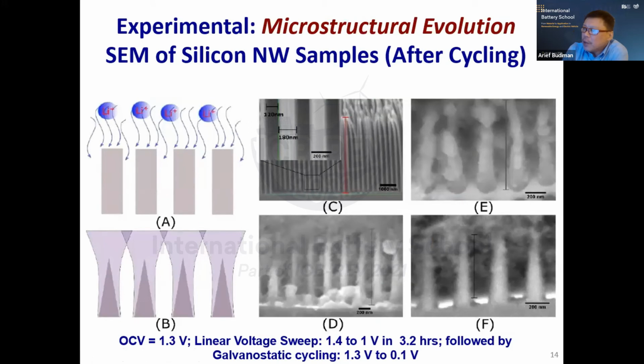Okay, so this is the sample, the microstructure evolution of the silicon nanowire during lithiation. This is real electrochemical lithiation, because many studies are simply chemical lithiation, which is not real lithiation. This is like what will happen in a real battery. So the lithium ion is being pushed into the silicon nanowire. Because of the geometry of the silicon nanowire, you see that it will expand first on the top, and only after that it will start expanding to the bottom. But at the same time, it will maintain the core of the nanowire still crystalline. And as I mentioned in the model that I discussed earlier, it remains very compressive. And that's basically what I verify with this experiment, the in situ lithiation.